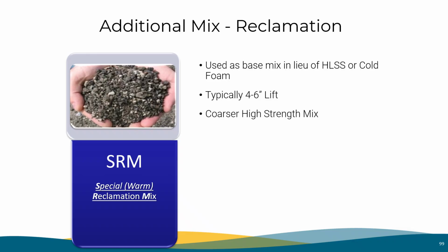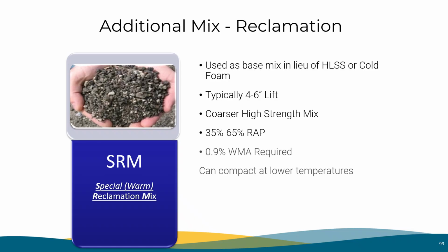It has a coarse high-strength mix, utilizes 35 to 65% RAP, and 0.9% warm mix additives are required so that it can compact at lower temperatures.